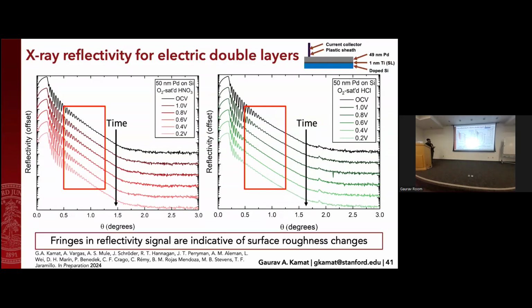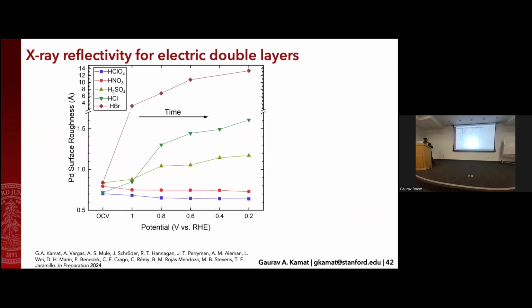And what that means is that there's surface roughness changes. Specifically, hydrochloric acid has a much larger role in roughening your surface compared to nitric acid. So if I take all of that data and back calculate what exact roughening is happening, this is what that data looks like. So nitric and perchloric don't really change the surface roughness. If anything, they get a little bit lower in surface roughness, whereas these other three induce a lot more changes.